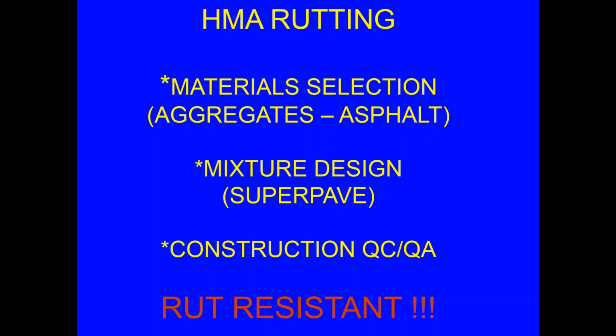How do you do HMA rutting? Material selection, do good aggregates work, do good mix design work, pick the right asphalt, and do good construction quality control and assurance. You'll get a rut resistant mix. Rather than trying to predict values within 1/10 of an inch or so, you know, how much is 1/10 of an inch, folks? Heck, you can hardly measure it, right? So if you put your effort into the mix design, material selection, and construction, you get rut resistant pavements, and that's what we're after.